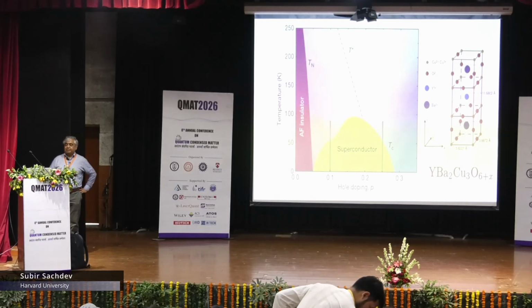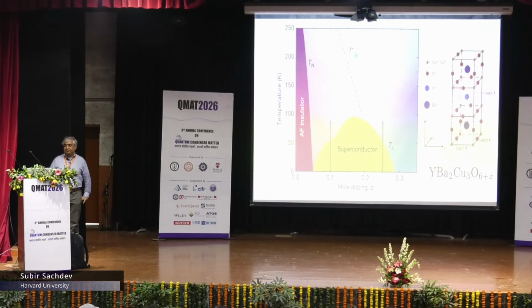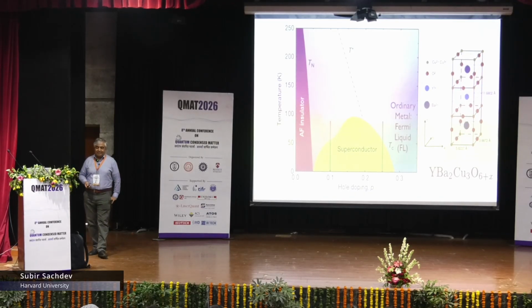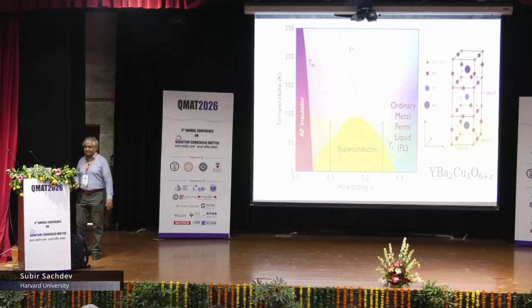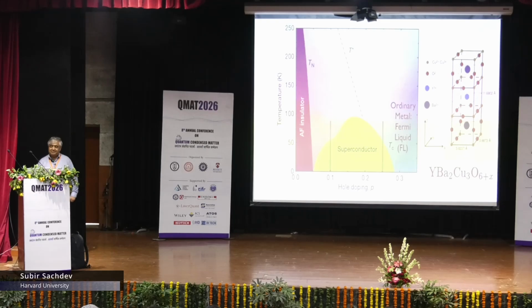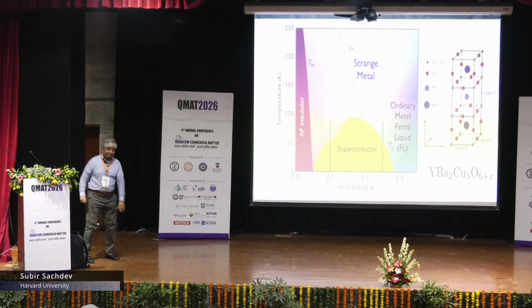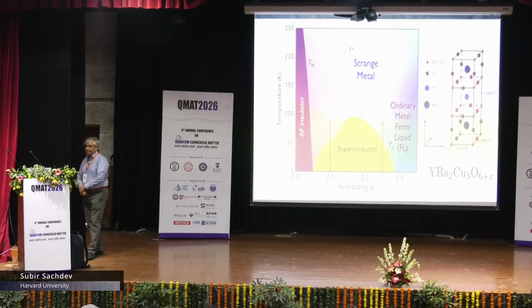So obviously one of the questions you can ask is, if you want to estimate TC, the natural question is, what is above TC? Because whatever is above TC is what's leading when you cool it to give you a superconductor. So if you look down here and you ask what's above TC, then you find what's called a Fermi liquid, where the Boltzmann theory I just summarized works perfectly fine. All right, but that's where TC is low. But when you look here, that's where this was a big surprise. Nobody predicted this. Nobody predicted these materials to begin with, and nobody predicted that they would show this strange metal. This was already seen in some detail in the 1990s, but has been studied a lot since then. So we have this strange metal where it's very clear to everyone, and that's one point that nobody disagrees, that Boltzmann theory doesn't really apply.